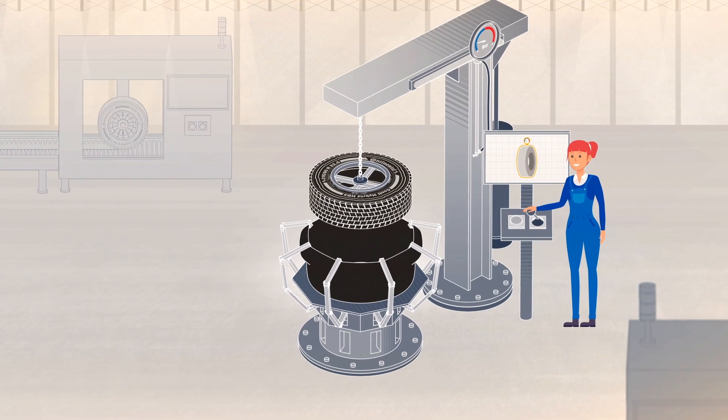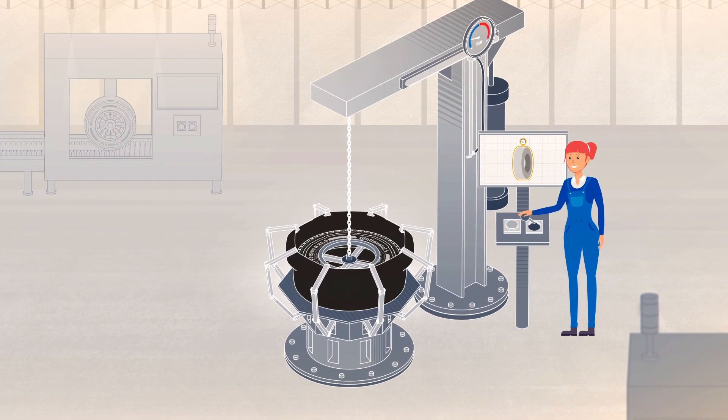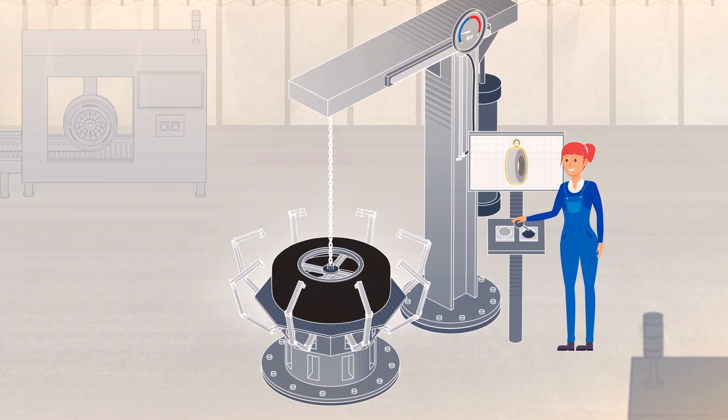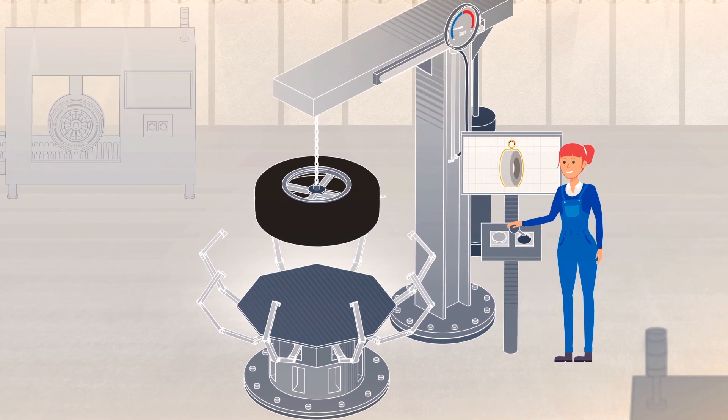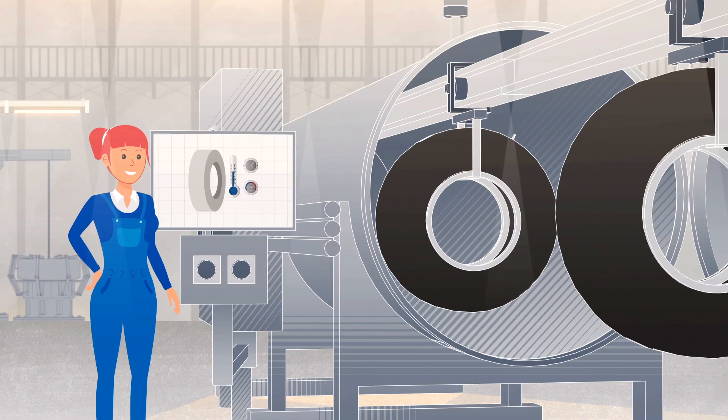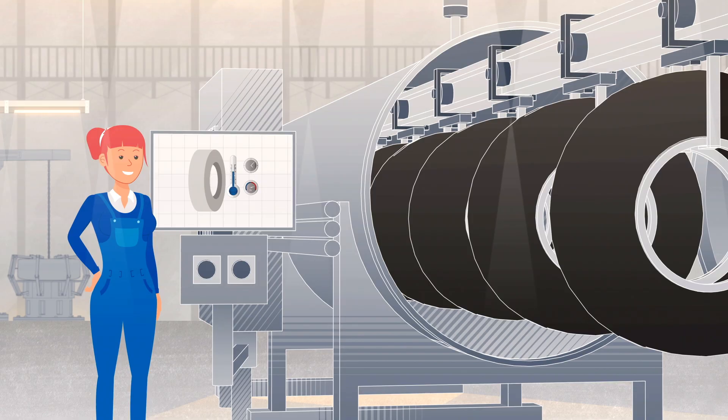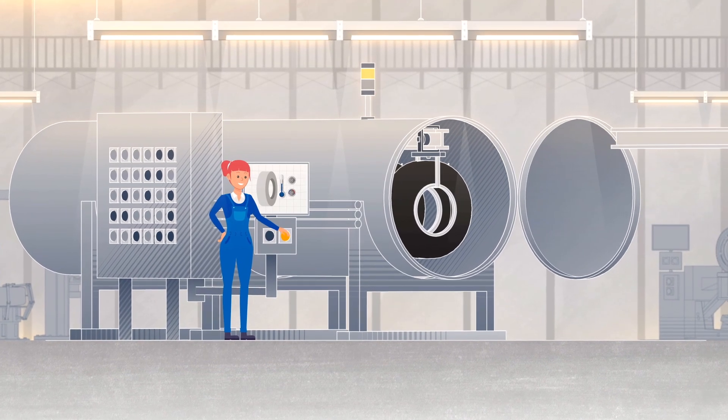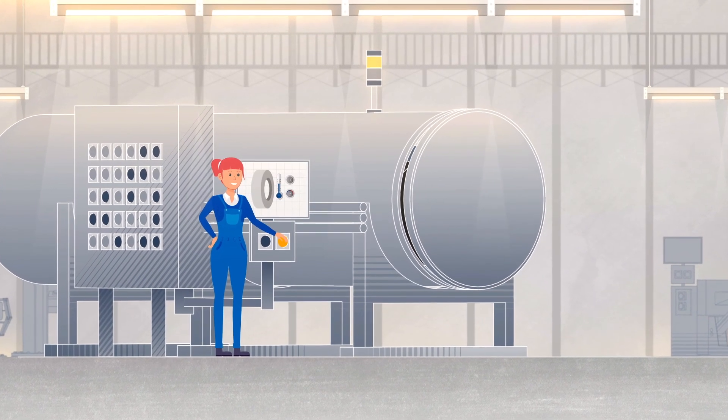Enveloping the tire aids the vulcanization process during which a vacuum is applied to ensure a constant pressure, keeping the tread rubber attached to the casing. Vulcanization requires a certain temperature, pressure and time to allow the cushion gum and tread to bond inseparably with the casing.